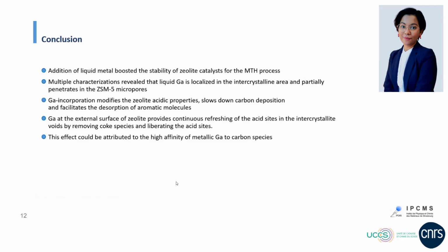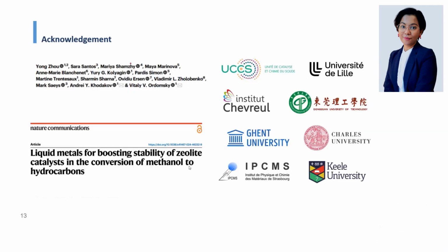And thanks to the presence of gallium, it provides a continuous refreshing of the acid sites in the intercrystalline voids by removing the coke species and liberating the acid sites, thus increasing the stability of the zeolite. And this effect could be attributed to the high affinity of metallic gallium to the carbon species.